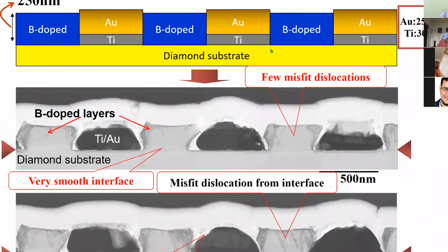So the selective growth has also been made. We make a metal mask, and then we get the boron doped layers, which in this case show 500 nanometers, that's the submicron region we achieve.